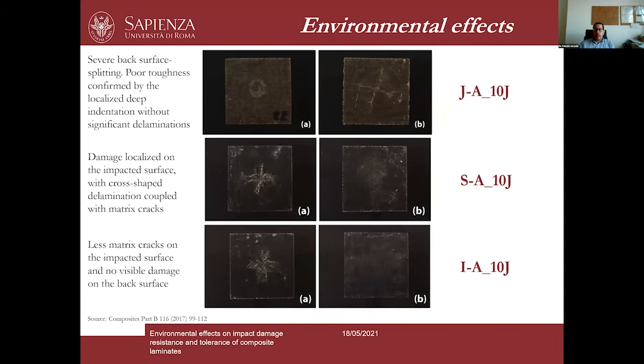And this is even more evident when we compare the damage modes that can be easily detected by visual inspection. Here you have again the comparison between the three different configurations: jute and the two hybrid configurations, all impacted at 10 joules. In this specific case, these are the results for the unaged specimens. Even an impact at 10 joules can create significant damage on the front and also on the back surfaces of these composite materials.